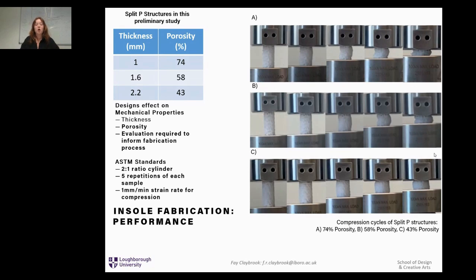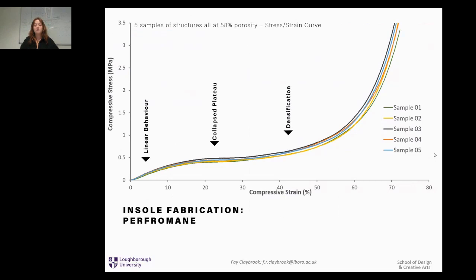So elastomers have complex mechanical properties from their deformable nature adopted by the material. Typically, more rigid materials will begin to deform with a linear profile before at a critical point the strain begins to increase for a near constant stress, which is a characteristic yield point of a material. This is a typical point of densification for compressed scaffold structures, whereby effectively all design porosity is removed from the structure. However, for elastomeric scaffolds, yielding does not occur and the scaffolds are able to return to their original form as long as there's no hysteresis in the structure.